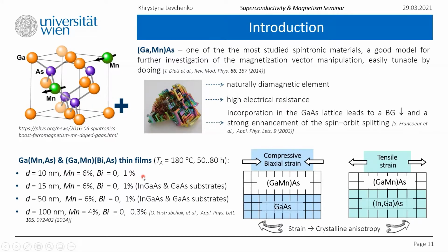Also, we have a different scheme of our sample growth. The typical method of growth is molecular beam epitaxy, or low temperature molecular beam epitaxy. For this, you need to have a substrate on which you grow the ternary compound. If you grow gallium manganese arsenide on top of gallium arsenide, you are introducing compressive biaxial strain to it, because the lattice parameters of gallium manganese arsenide are larger than those of the layer below. So we are trying to compress and squeeze the top layer to fit the bottom one.